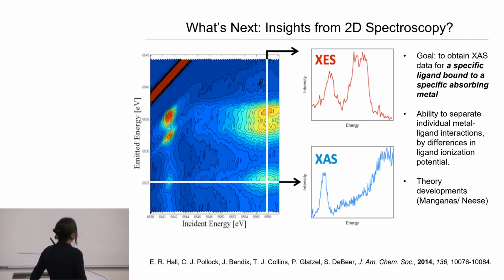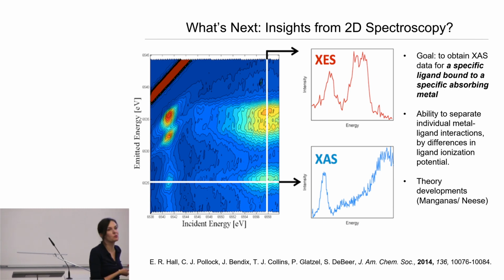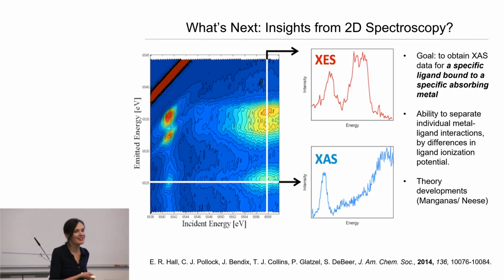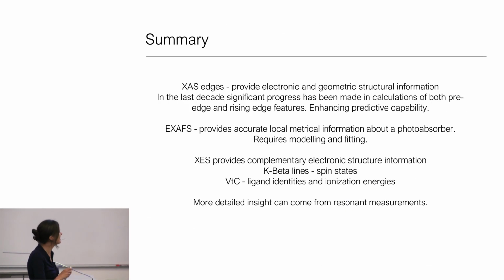And then finally, another experiment that largely remains a demonstration was early work that we did, starting to think about this as a way to get ligand selective X-ray absorption. So the idea would be that you sit at a valence to core emission feature that's assigned in this case to a nitride, and you get the XAS just from that feature. Again, lots of challenges in terms of understanding these spectra in terms of theory and experiment, but you're here in Mülheim, and I also just want you to have some idea of the spirit of what drives us, and normally how long experiments are in the making, because this paper's 2014 and we're still working on understanding some data that were collected around that time.